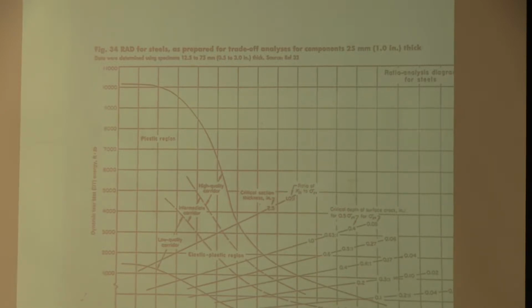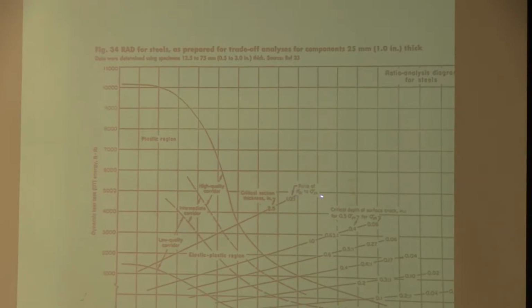You don't want a brittle fracture where it shatters like glass and sends shrapnel all around in a pressure vessel or a submarine, which is also an externally pressurized pressure vessel. But you get down here to 300 KSI steels, and your critical flaw size is 1/10 of an inch, okay? It turns out you'd like to have a ratio of toughness to yield strength, K squared over sigma, of 2.5, which is kind of the difference between your plastic deformation region and your plane strain region.